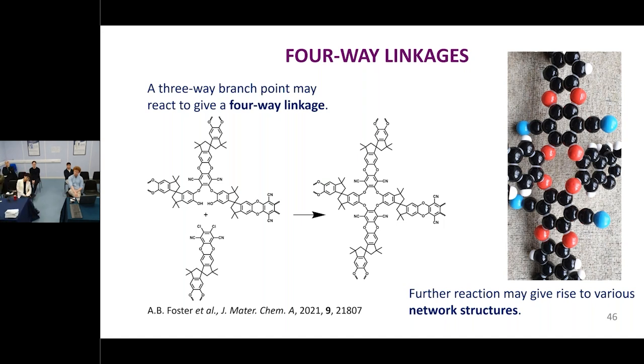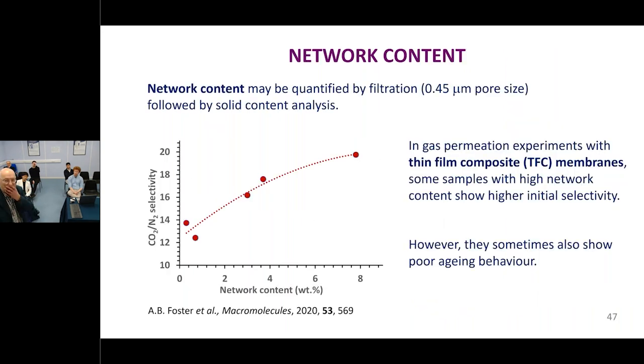If we've got these branch points, we can actually get further reaction if you push it too far, and we can then start to build up different types of network structure. And again, that can have an influence on the properties. We can quantify the amount of network above a certain size just by simple filtration experiments.